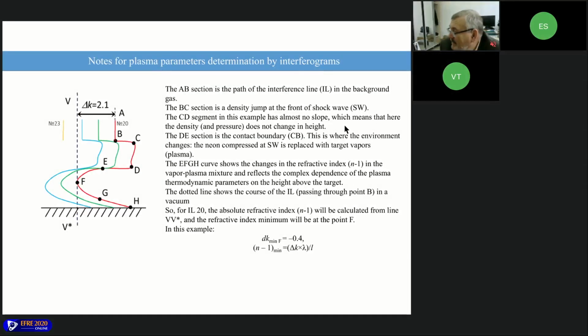And I want to note the path of interference lanes. In AB, these are the interference lanes number 20, 21, 22, 23, and the dotted dashed line. V is a vacuum lane. For lane number 20, the absolute refractive index is calculated in this example. The delta K minimum is minus 0.4.